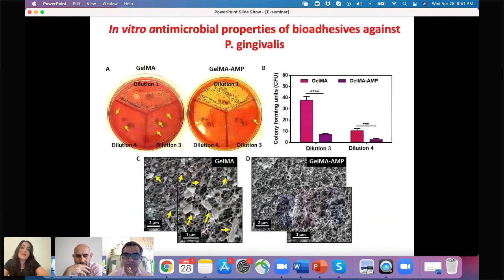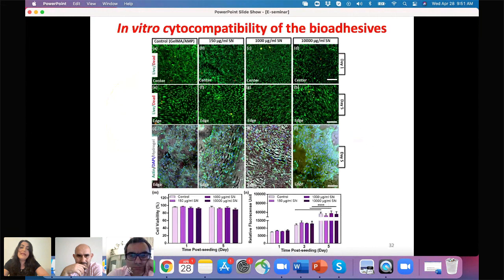We also did an in vitro antimicrobial test on these bioadhesives against P. gingivalis, and we show that as we introduce antimicrobial peptide in our hydrogel, we can form an antimicrobial adhesive biomaterial. Here is a representative SEM image of the bioadhesive without AMP, showing that the bacteria can grow inside the gel. Once we introduce AMP at optimized concentration, we can prevent bacteria infiltration inside the bioadhesive. We next tested the in vitro cytocompatibility of the bioadhesive.